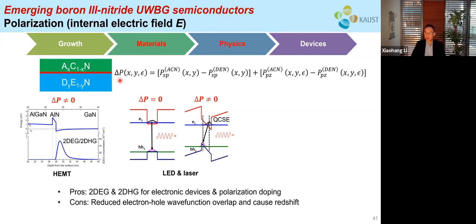And the delta P here is a function of the composition X and Y, as well as epsilon, which is strain of those layers. It is equal to the difference between the spontaneous polarization plus the difference between the piezoelectric polarization under the strain. And this delta P is fundamental for the devices used for 5G communication and power management today. Because without this delta P, there will not be any self-induced two-dimensional electron or two-dimensional hole gas for the gallium nitride transistors.